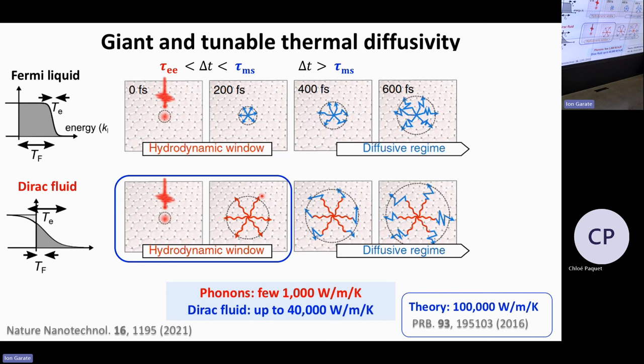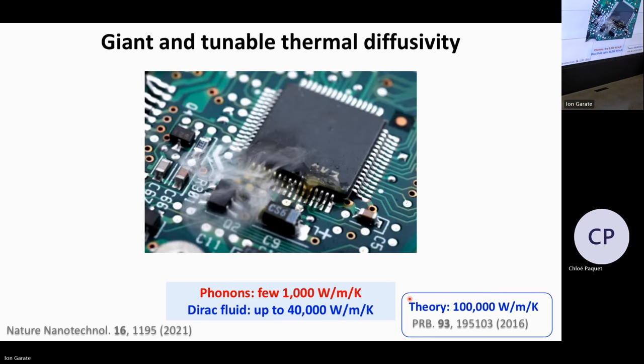So that is not completely crazy. There were actually already theoretical predictions of numbers like this. And in fact, it just diverges the closer you get to the Dirac point. So you can get extremely, extremely large thermal conductivities in the system. Now, all at room temperature. So it's the first room temperature observation of hydrodynamic heat transport of electrons, at least at that time. There was one exactly at the same time, using tip-based studies.